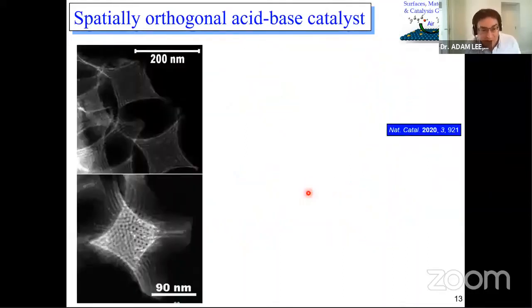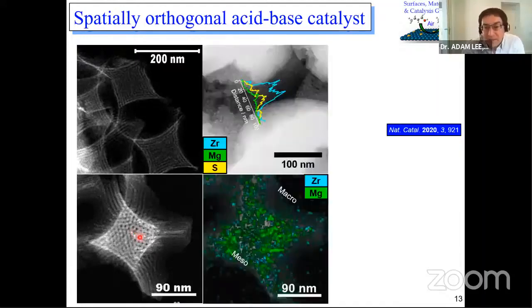How do you know I've made the thing I say I've made? Well, let's look at some TEM images first of all. So here you can see the macropores, this large curvature here. That's one section of the macropore. And you can see in between the macropores, we have these mesopore arrays. Each of these holes here is about 5 nanometers across. And it's those that are decorated by magnesium oxide.